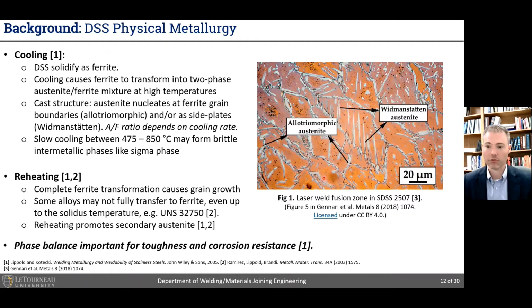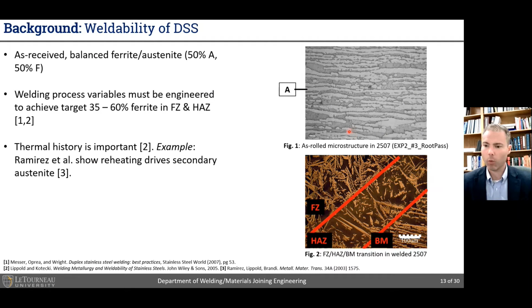Bottom line is that controlling phase balance, and our typical target would be 35 to 60% ferrite, is really important to achieve our desired toughness and corrosion resistance for these materials. So if we think about weldability then, in a typical wrought or rolled type plate, we would see this sort of microstructure with a balanced ferrite and austenite phase. And our target and ideal properties would be, in this case, of 50% austenite, 50% ferrite.